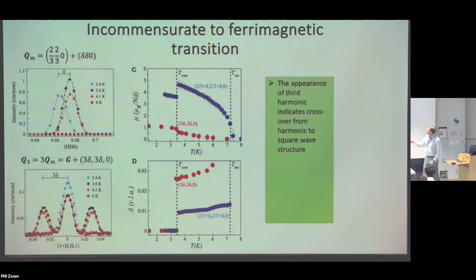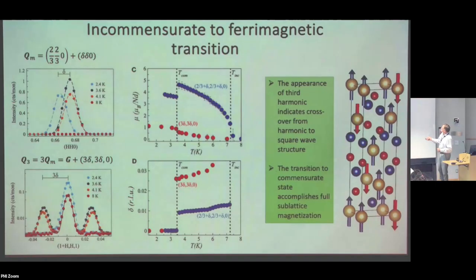And actually what happens is that these higher harmonics at low temperatures go away, and then they become the ferromagnetic part of the Bragg peak. So this ferromagnetic moment is what it becomes, in a sense, associated with the higher order harmonic, which then goes away. So this is roughly what the spin structure looks like. The spins are mostly along the c-axis, because that's what the crystal field, Kramers doublet ground state, specifies, if you will.